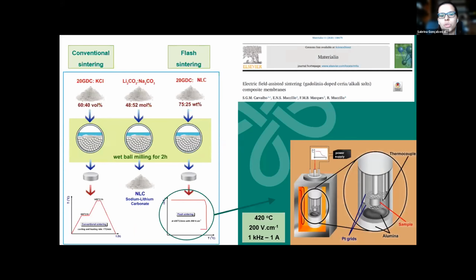So the materials used for the membrane were Gadolinia-Doped Ceria for the ceramic phase and a eutectic mixture of sodium lithium carbonate for infiltration. And the membranes were prepared by two different methods. The traditional one, where we cold press the mixture of Gadolinia-Doped Ceria with a pore former. Then the pellet was sintered and infiltrated with the molten carbonate.